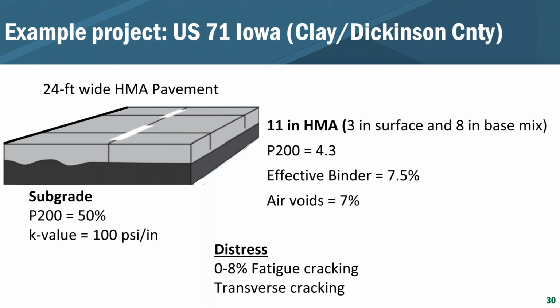So with this pavement, it was a full depth asphalt pavement, 11 inches thick. And in Iowa, what they do is they mill the profile into the asphalt so they don't have overruns of the concrete when they place the concrete afterwards. So what Chris and Ben were projecting would be a maximum of about 3 inches of AC would be removed from the surface. Now, with the design that they have, the upper 3 inches was a surface layer, and then the lower 8 inches was a base mix, which makes it nice too, because then you're relying on a base mix and not so much on the surface layer for carrying the load. Because we all know the surface layer, of course, is just to cap off that, and we carry the load with the base mix. But either way, it was an 11-inch section right on top of the subgrade, and 3 inches of that was the surface layer, and 8 inches of that was the base.